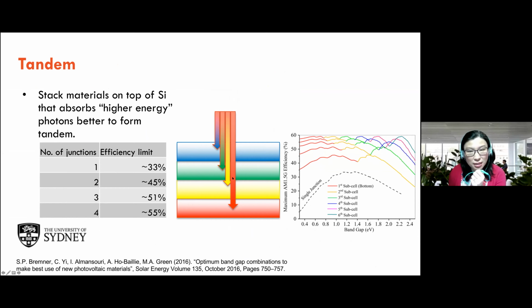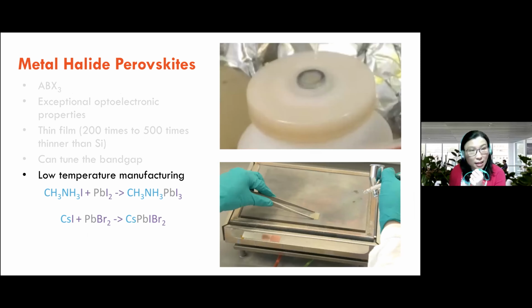And then you stack them together and you can see the efficiency keeps increasing if you increase the number of junctions. But as you increase the number of junctions to say beyond 5, or even beyond 4, beyond 3, you'll see that the increase is marginal. So that's the beauty of perovskite, because you can tune the band gap, you can actually use them for tandem cells. Another beauty of perovskite is,